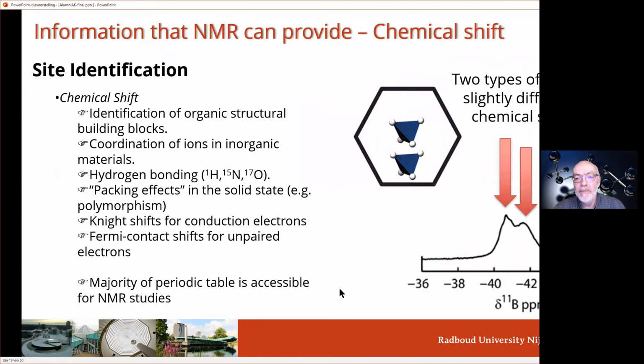Okay, so in our case, when we look at our boron hydride in the silica, in the nanopores, we see that we have two different chemical shifts. And the chemical shift really allows us to identify different structures. For instance, different organic structural building blocks. That is what the organic chemists use to identify their molecules. The coordination of ions in inorganic materials, but in our case, they are both BH4.